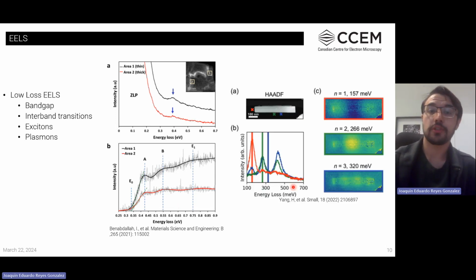Another example to show the benefit of doing STEM EELS in general, which is exploring the spatial distribution of these kind of excitations, is coming from this work on infrared plasmons. In this case, we're seeing here a nanorod that is a few hundred nanometers long and 50 nanometers cross-section, of lanthanum-doped barium tin oxide.